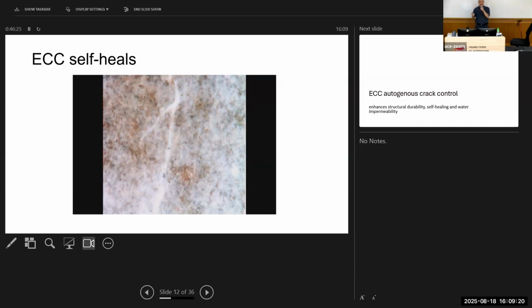we think that the fibers are actually helping in terms of doing this self-repair job. How does it help? There are lots of fibers crossing the microcracks. These fibers themselves are very tiny, roughly about 30 micron, depending on whether you're using PVA fiber or PE fiber, down to about 12 microns. So you can get thousands in a very small square centimeter cross section. There are thousands of fibers crossing it. So if you look close enough, you actually see a forest of tiny, tiny tree trunks crossing, right? There are many, many of them.